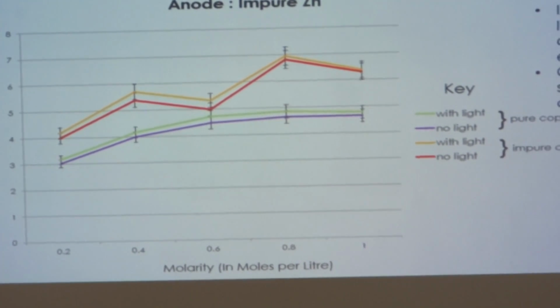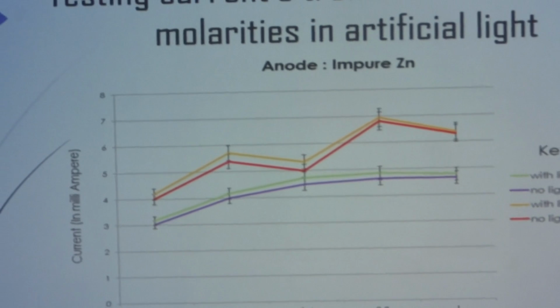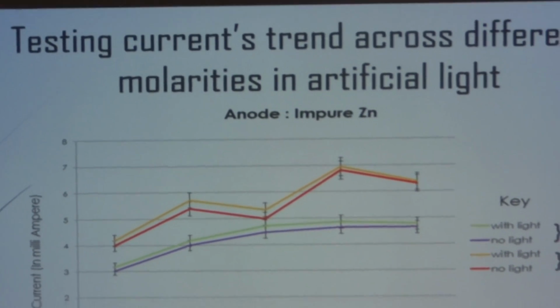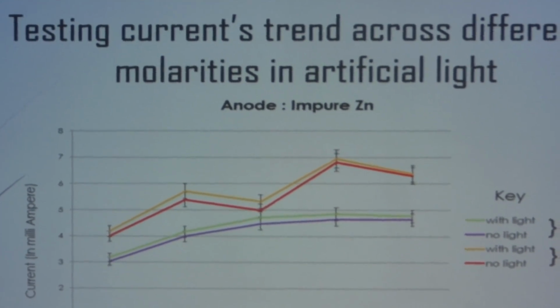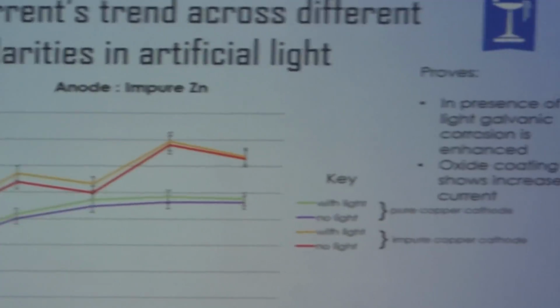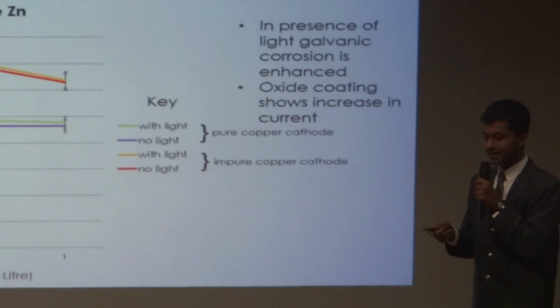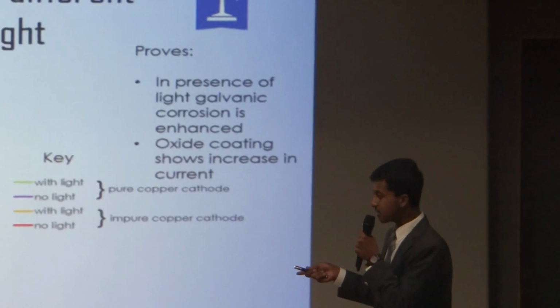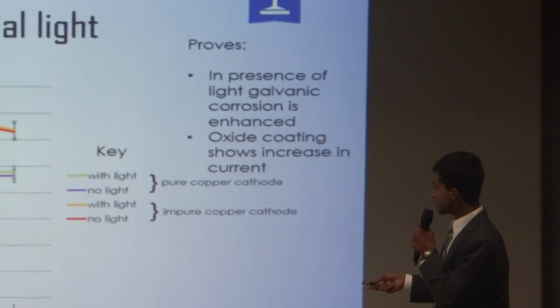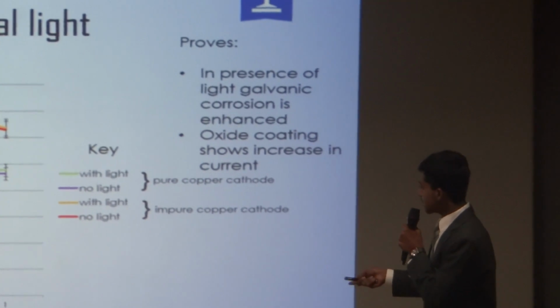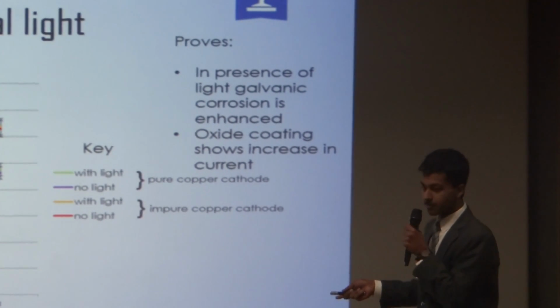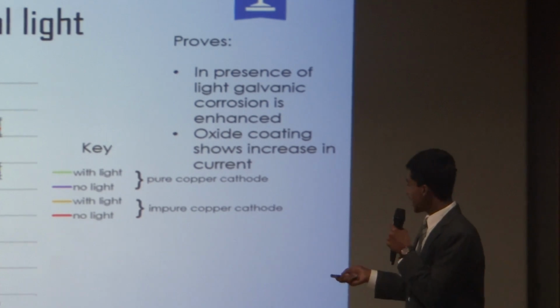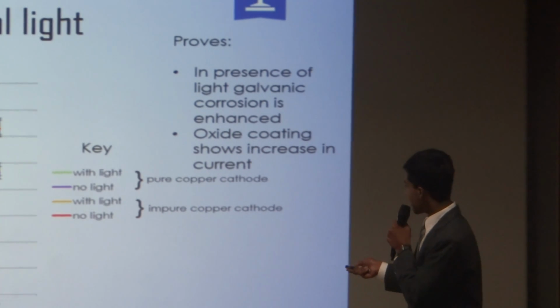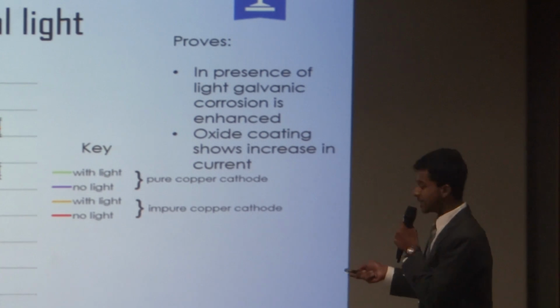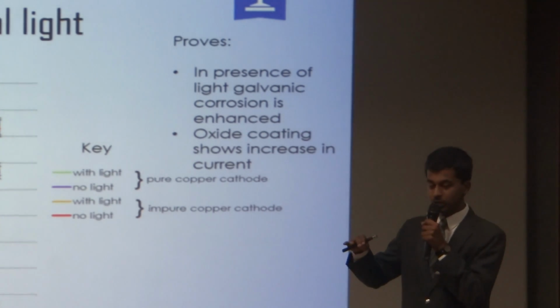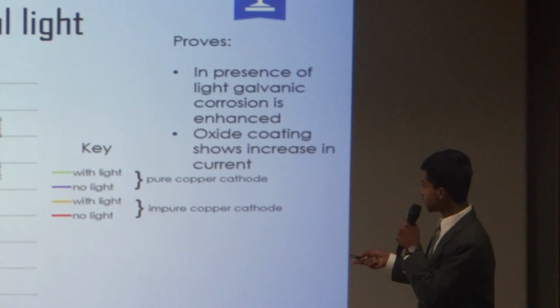So what we did was we took zinc as our new anode, and then we tried the same experiment, the same setup again. So the first combination you can see over here is with taking pure copper as cathode and impure zinc, the different metal, as anode. So what you can see is that as the molarity increases, so does the current in its degree. And what we can also observe is that when there is presence of light, there is a certain increase in the current which we noted even in the impure combination.